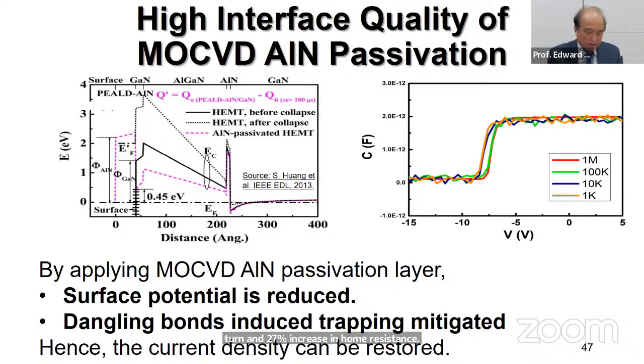And then we can see the high interface quality of this nitride passivation demonstrated in this view graph. The surface potential is reduced using this passivation layer, and then the trapping induced by the dangling bonds is mitigated because you don't see much hysteresis. So the high current density can be restored using this aluminum nitride passivation layer.